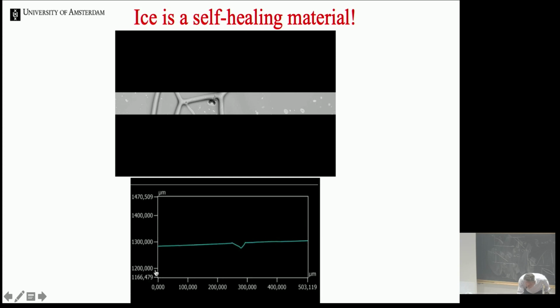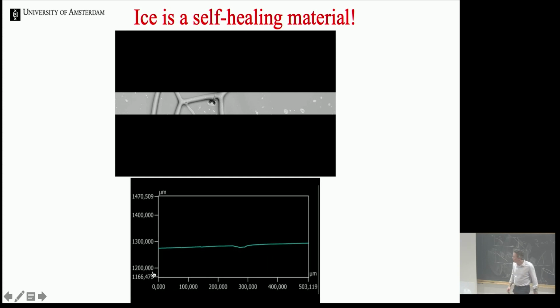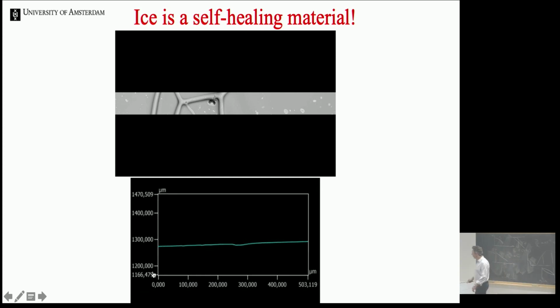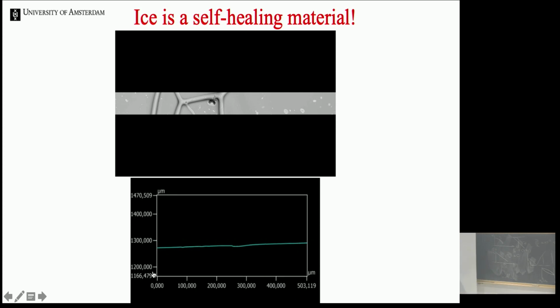And so this is the quantitative measurement. You see that we had this dent here, and so this is a cut through the scratch, and you see that indeed the scratch heals, and the surface is really, really flat. Which helps with my explanation of the little ball-bearing balls, because if the surface was rougher than the size of the ball-bearing balls, this wouldn't work. For this, I will show you in a second.